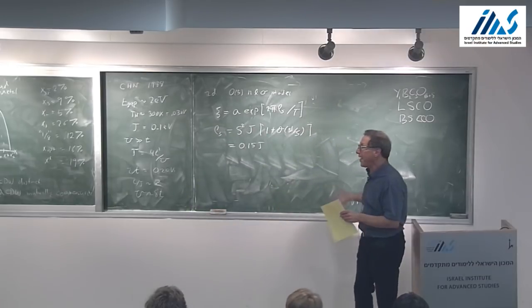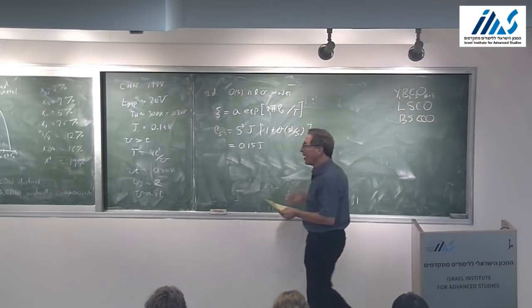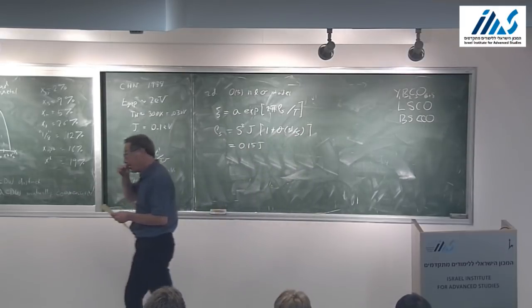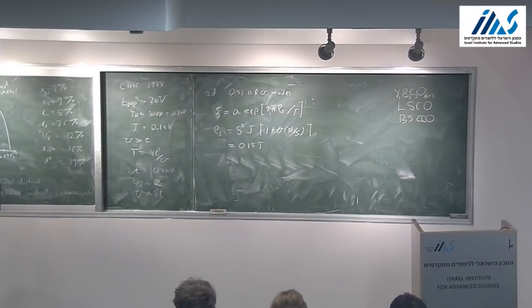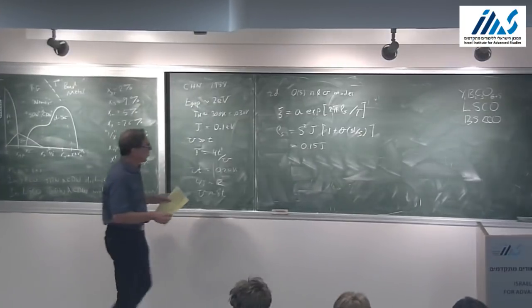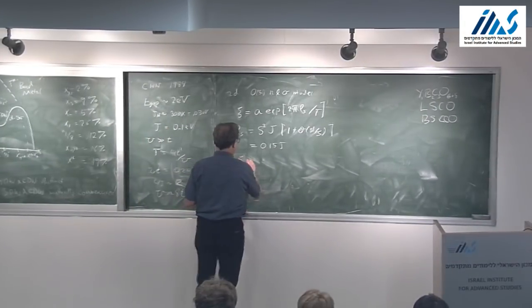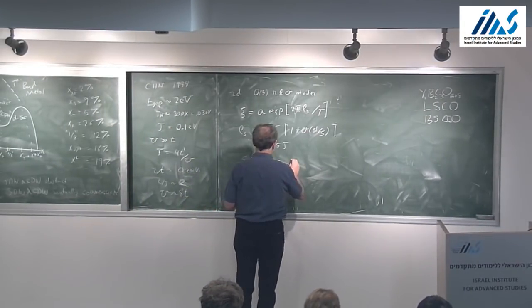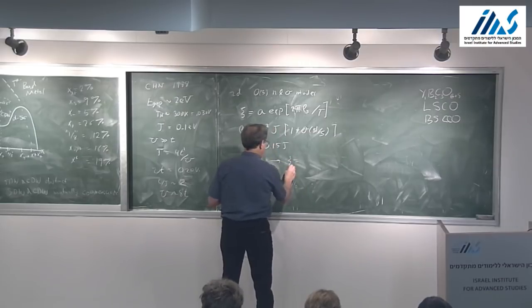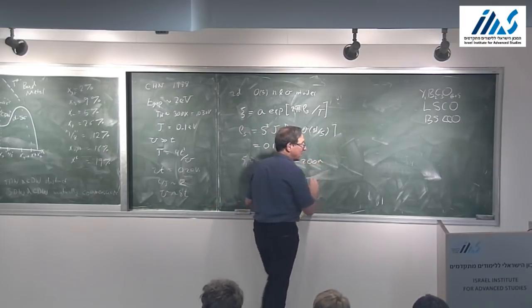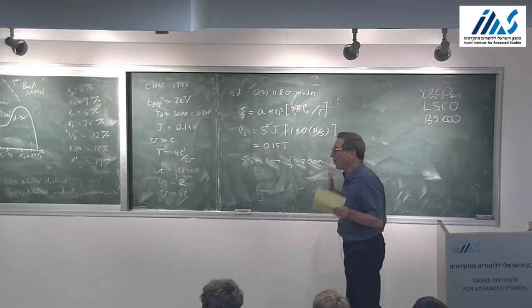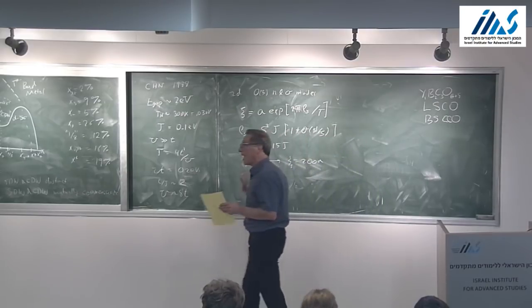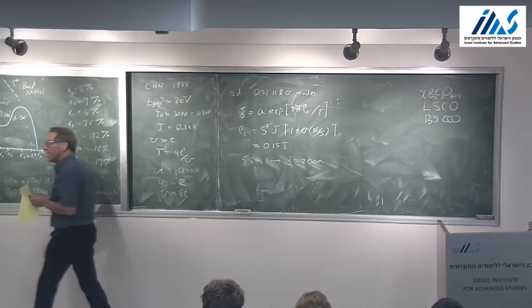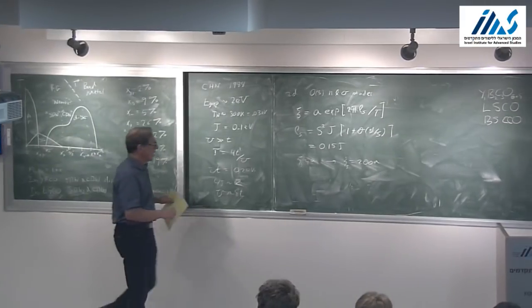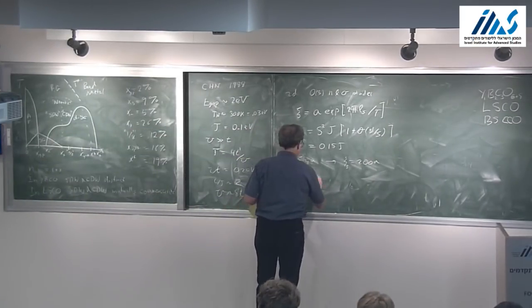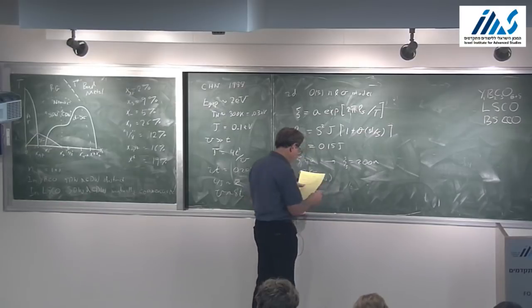And then could fit the correlation lengths measured by neutron scattering as they grow over a large dynamic range, from xi of the order of 1 up to xi of the order of 200 lattice constants. That's really impressive. You can do dynamic scaling to get an understanding of the spin structure factor, S of Q and omega.